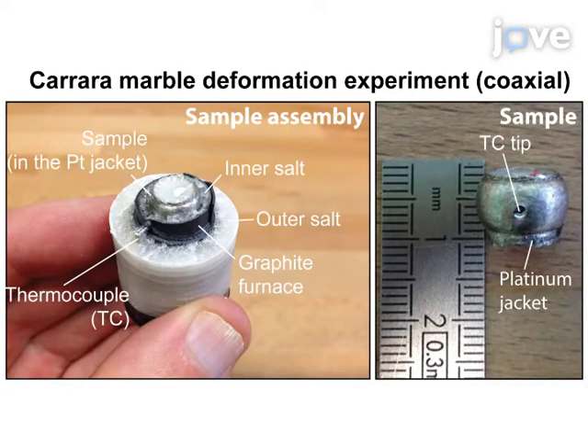Representative results of Carrara marble deformed at 700 degrees Celsius and 1.5 gigapascals are shown here. This includes a scheme of the deforming sample assembly and the stress versus time curve produced during the deformation experiment. At first, both the pressure and temperature are increased alternatingly during the pumping stage. While the sample assembly is heated by using the Joule effect, both rams transmit forces to actuators and pistons that